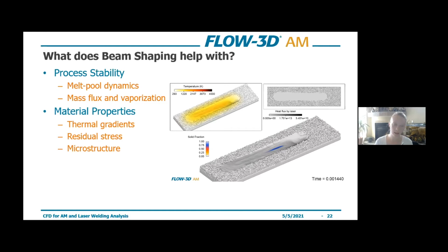Ultimately, process stability is useful for getting the desired material properties in the final part. So we want to have better control over thermal gradients, less residual stress, better microstructure control. So all of these things are a little bit easier to maintain when you have more flexibility in your heat flux distribution. And then productivity as well. So when you're increasing the area of your heat flux distribution, oftentimes this can lead to printing over larger areas, increasing your scanning speed. You can also have more optical flexibility with beam shaping, especially with some of the new technology that's coming out with in situ kind of beam shaping techniques, defocusing, things like that.